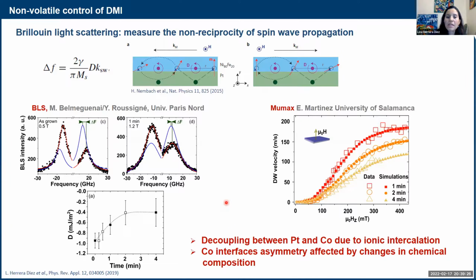But then, of course, that's not the end of the story. We have seen that in charge effects, if you bias the top interface only, you could still get effects. And we know very well that here we also bias the top interface very much. So it is really a combined effect between what we do in the top interface and the bottom interface.